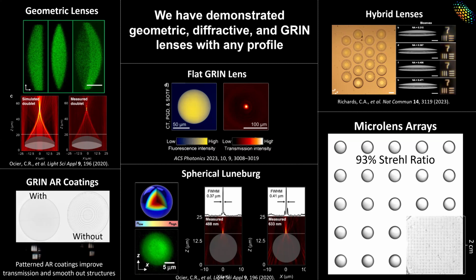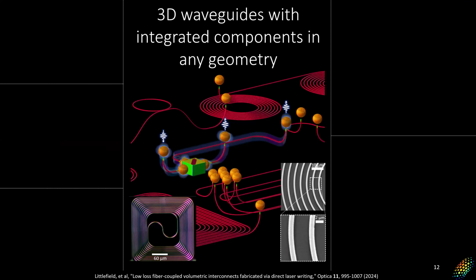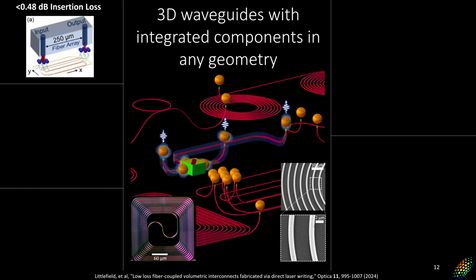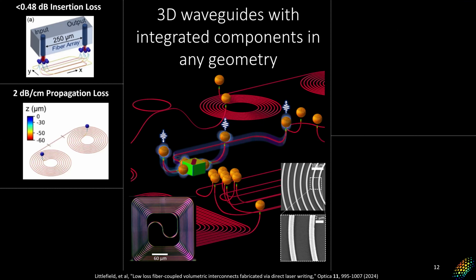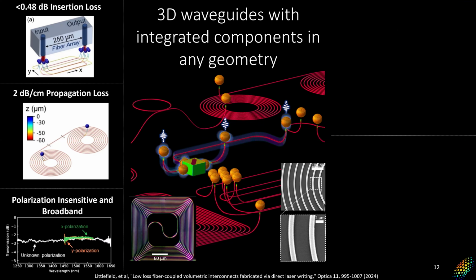Okay, so in addition to lenses and free space components, we can also do essentially 3D waveguides and integrated components in any geometry. We've been able to demonstrate fiber to 3D waveguide interconnects with less than 0.5 dB insertion loss, and I think there's even a lot of room for improvement there. The waveguides have been demonstrated with about 2 dB per centimeter propagation loss. Again, I think there's some room for improvement there.